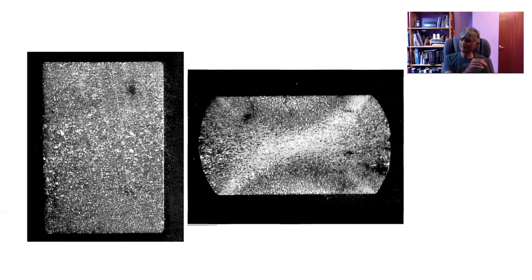I can show you this really quite elegantly on a macroscopic sample. This is a sample which during its austenitic state was flattened into this shape. So you can see that this has barreled out, and therefore the plastic strain distribution is not homogeneous. The maximum plastic deformation happens in this X-like region. And therefore, we will see in the next micrograph that bainite hardly forms in this region because the austenite has been stabilized by dislocation debris. Whereas here, where there is zero plastic strain, you will get lots of bainite.